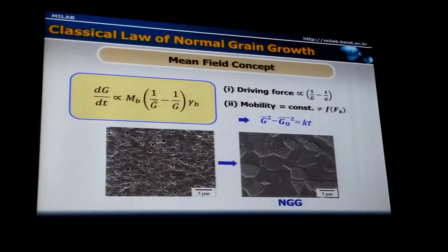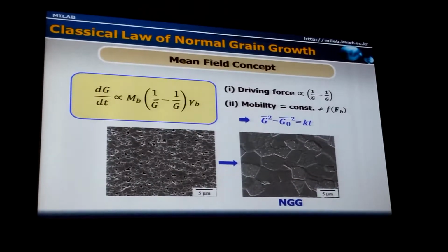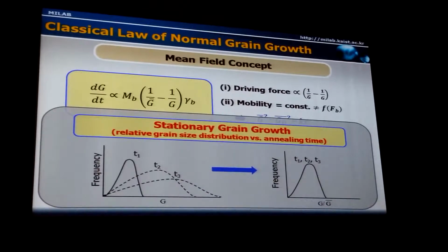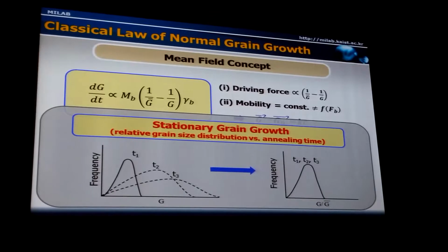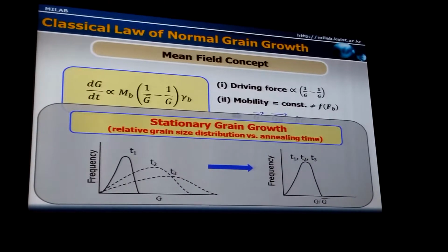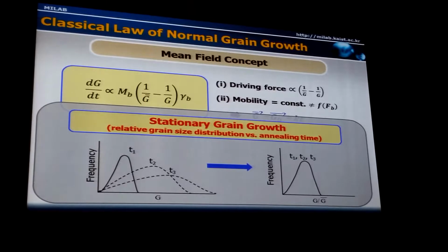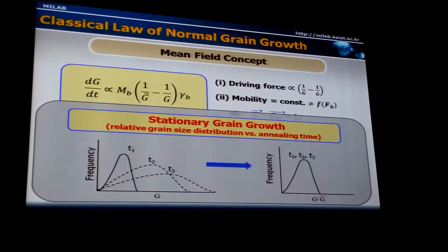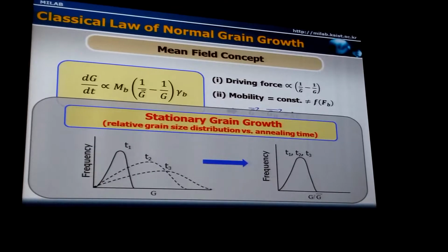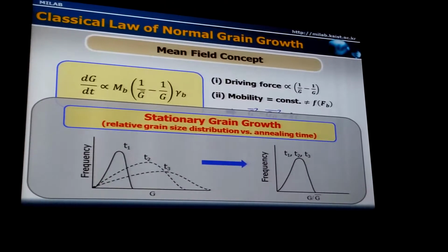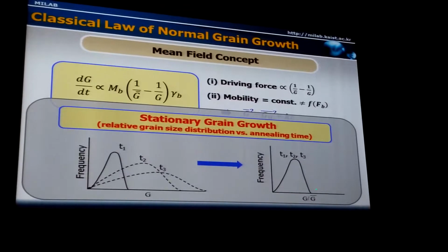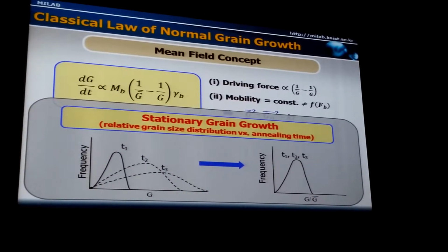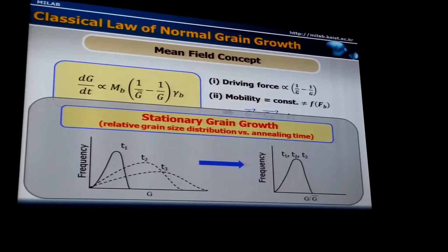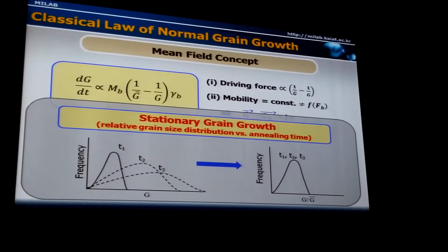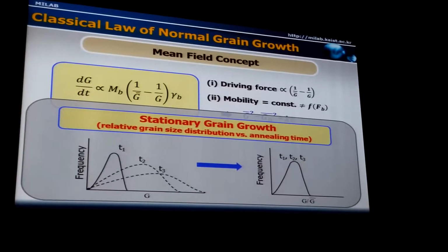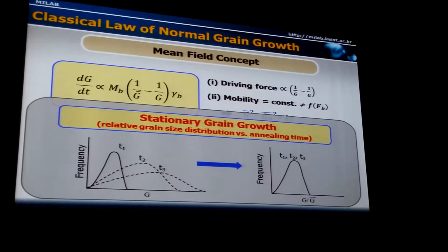And so grain coarsens as we increase the annealing time. One of the characteristics of normal grain growth is that the relative grain size distribution does not change with the annealing time. When you plot the grain size distribution, of course, it broadens with increasing annealing time. But when you plot it relative to the average grain size, the distribution is invariable, showing stationary grain growth behavior. This is an important characteristic of normal grain growth.